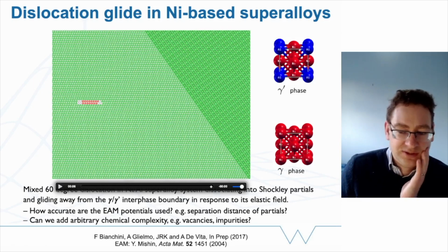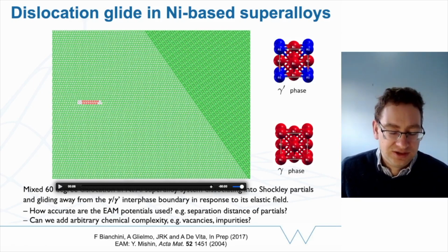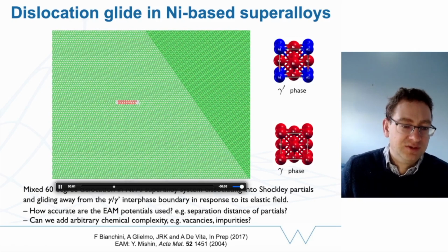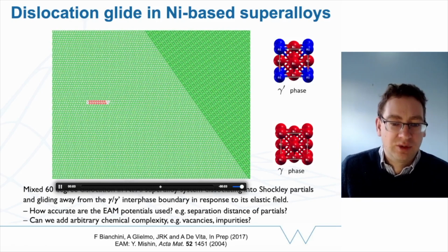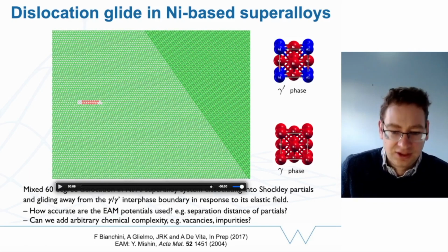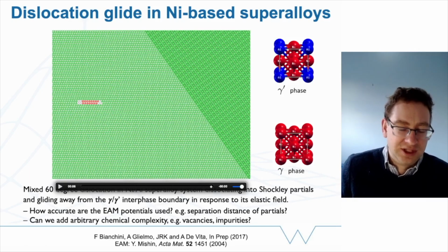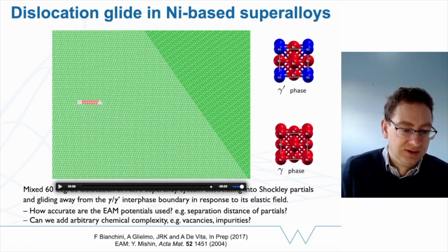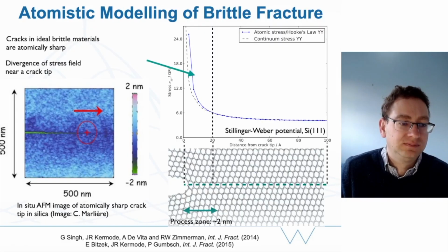It's a bit like bricks and mortar that make up a wall. The superalloy is made up of a gamma phase, shown on the left-hand side, where my dislocation is moving around, and a harder gamma prime phase which has got extra aluminium in it and is tougher, and the dislocations can't get inside that part. And we'd like to understand why that is and improve the properties of the material and improve the accuracy of the modelling as well.